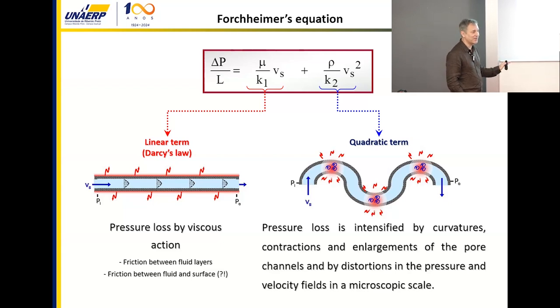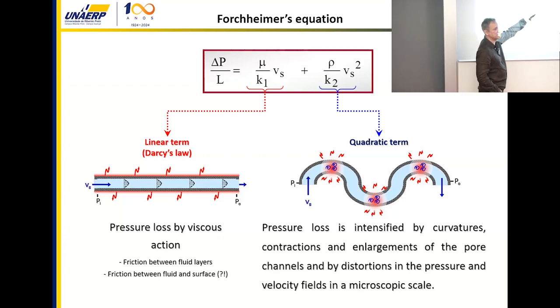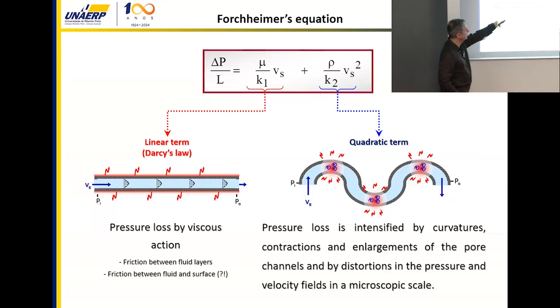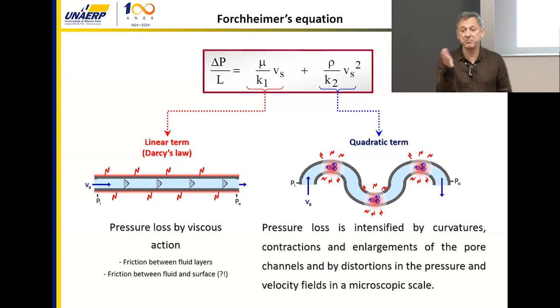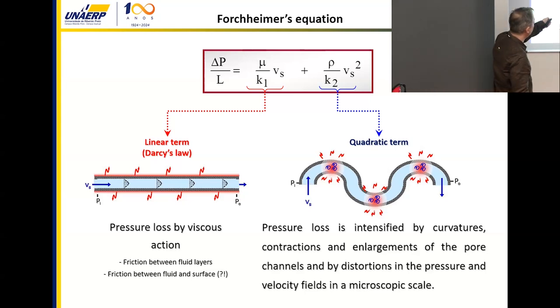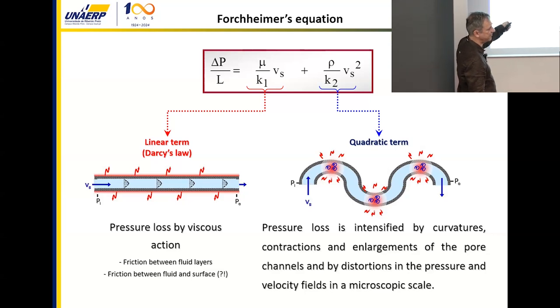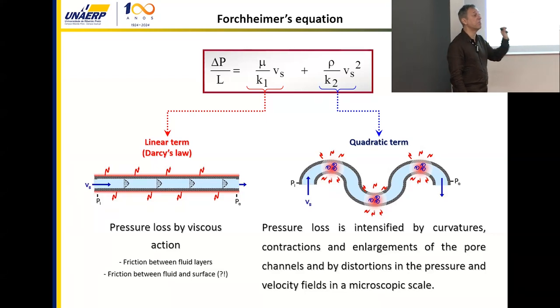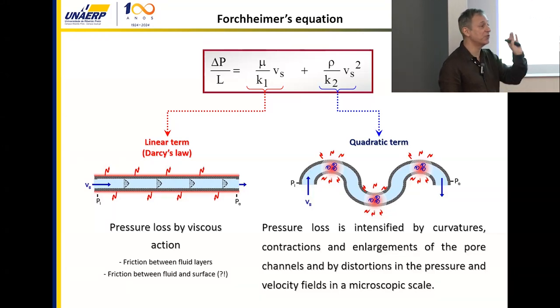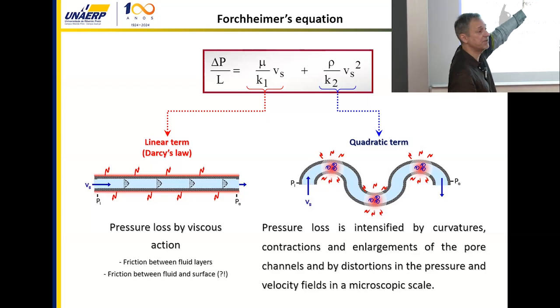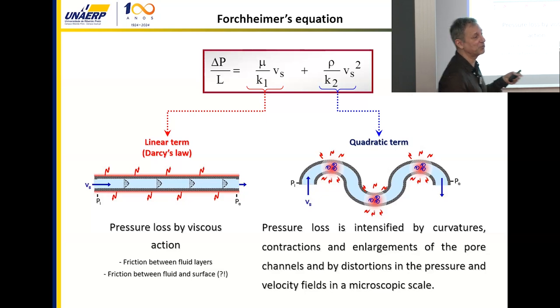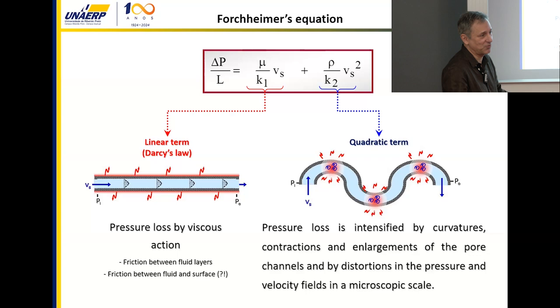Never try to fit Darcy's law at the beginning. Always try to fit this, and then if you want, you can take out this term. But for example, for molten metal filtration, 90-95% of the total pressure drop comes from this. If you take a facial mask or a membrane, for example, for filtration, normally a facial mask is about 85% from here and 15% from here. There's a number, Bernardo, called the Forchheimer number. If you take this Forchheimer number, you know exactly the percentage of contribution of each term. Then, if you want, you can disregard one. But normally I don't disregard because I already have the two terms, so I don't need to take out any.